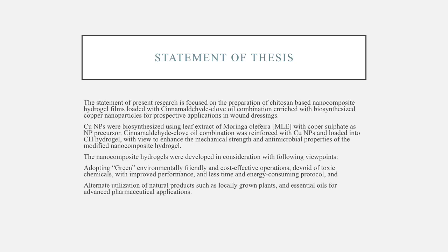Copper nanoparticles were biosynthesized using leaf extract of Moringa oleifera with copper sulfate as a nanoparticle precursor. Cinnamaldehyde clove oil combination was reinforced with copper nanoparticles and loaded into the chitosan hydrogel films with a view to enhance the mechanical strength and antimicrobial properties of the modified nanocomposite hydrogels.